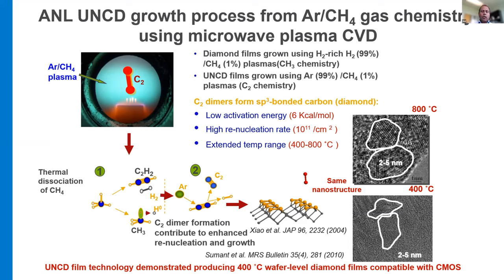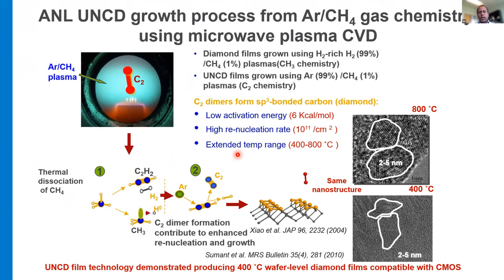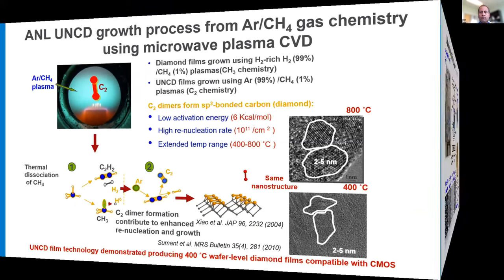This gives rise to a very high renucleation density, about 10 to the 11th nuclei per centimeter squared. Because of the high renucleation rate and the low activation energy, we can insert these C2 radicals into the diamond lattice, and we can have a very extended temperature range, from 400 to 800 degrees Celsius. This is one of the important aspects of this growth process, that we can produce diamond at about CMOS compatible temperature while still maintaining the phase and purity of the diamond.